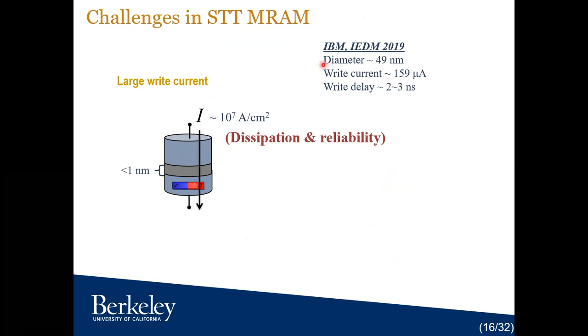So this is data from IBM from last year's IEDM. They demonstrated an MTJ with a diameter around 50 nanometer, quite small. So this is promising for density scaling. And their write current was around 159 microampere, and switching was very fast, just a few nanoseconds. But if you translate this current into a current density, it is 10 to the power 7 amp per centimeter square, and that's quite large.